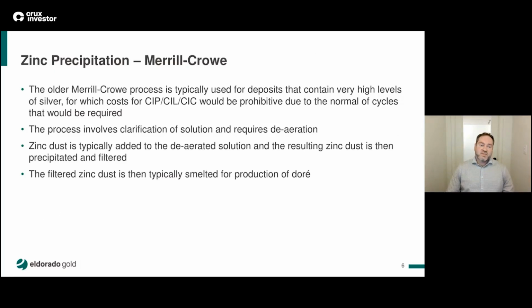This process is older and typically less advantageous unless you have a high silver content in your deposit, and that would require significant costs to be operated as a CIP or CIL circuit. It requires clarification of the solution as well as deaeration. After the solution has been clarified and deaerated, zinc dust is added, and the resulting zinc dust, which is now formed with gold, is precipitated and filtered, and then smelted to produce doré.